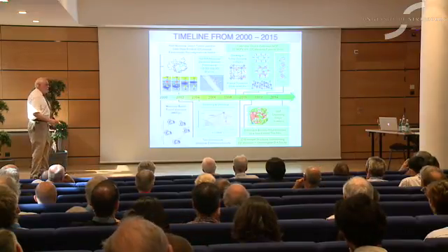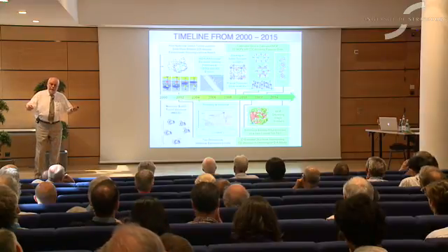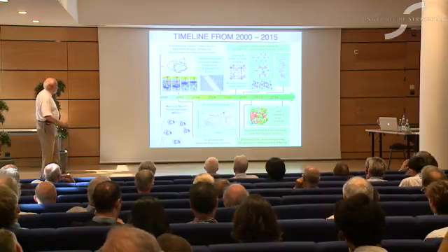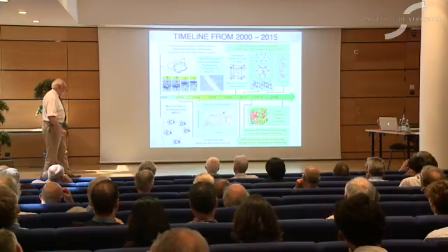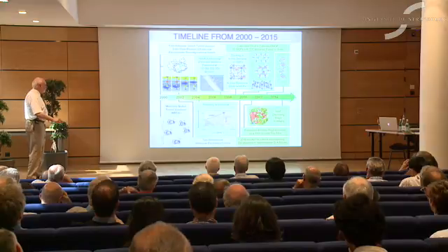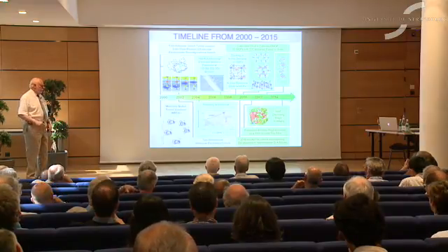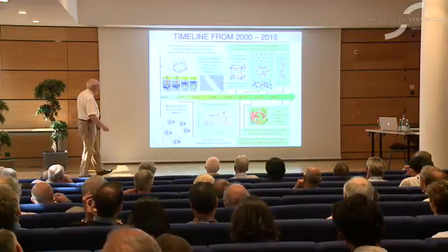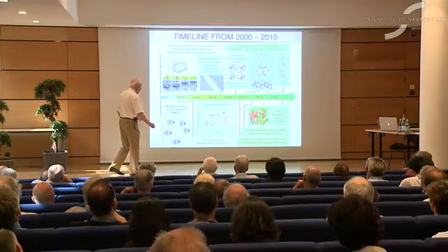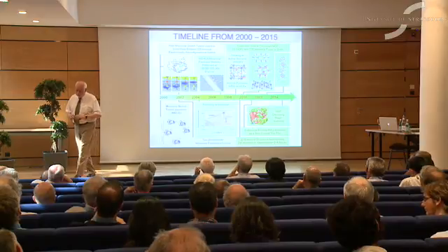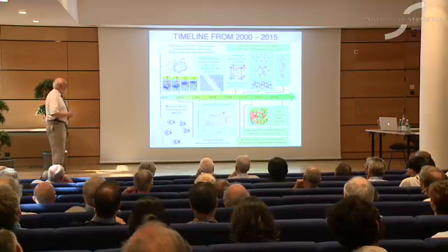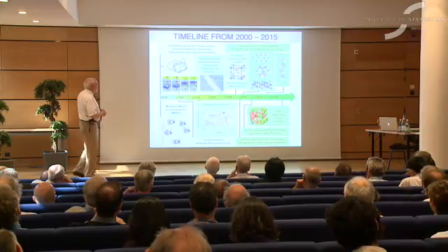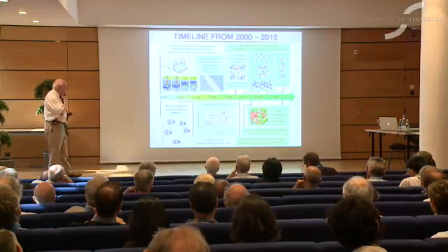In solution, it was something like 16 kilocalories per mole, so it lasted for about a second. By the time we got to a sandwich, a molecular switch tunnel junction, it was taking an hour, associated with a barrier of 22, 23 kilocalories per mole. But the downside is that switches would die after about 100 cycles, and so we've been looking ever since to introduce more robustness.